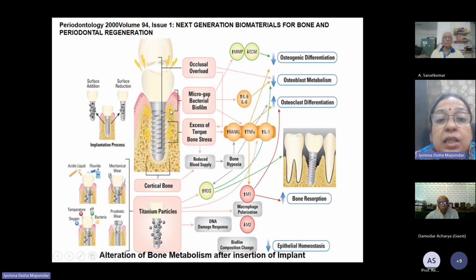In addition to that, there is also typical crevice corrosion, as well as tribocorrosion phenomena due to constant chewing action. So you cannot keep yourself at rest after implantation. At least after 4 or 5 days you have to go on with your own activity. If the chewing action is more, you will find more problems of tribocorrosion, and there is also occlusal overload.